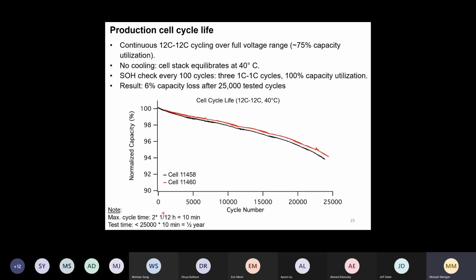The good thing is it only takes them about half a year to run a test like that, because if you charge at 12 C, a charge only takes 1/12 of an hour maximum. You can multiply this by 2, so it's only 10 minutes for a nominal 100% capacity cycle. So this testing takes about half a year. The cycle life is quite incredible.